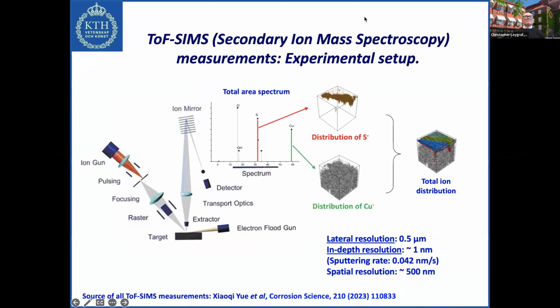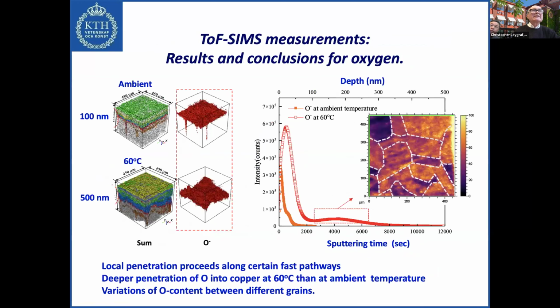Okay. Well, the point is that by this ion gun and the optics, you scan not only laterally along the surface, but you scan also as a function of depth. And with this technique, you cannot really tell if these areas for enhanced penetration, like this one, are grain boundaries. You can see here that there is something which could suggest that this is a grain boundary. But in fact, you cannot tell this surely by the time of flight SIMS measurements. You have to combine this with the other techniques that we have been using, so that you are quite clear that the areas are really grain boundary regions and nothing else.